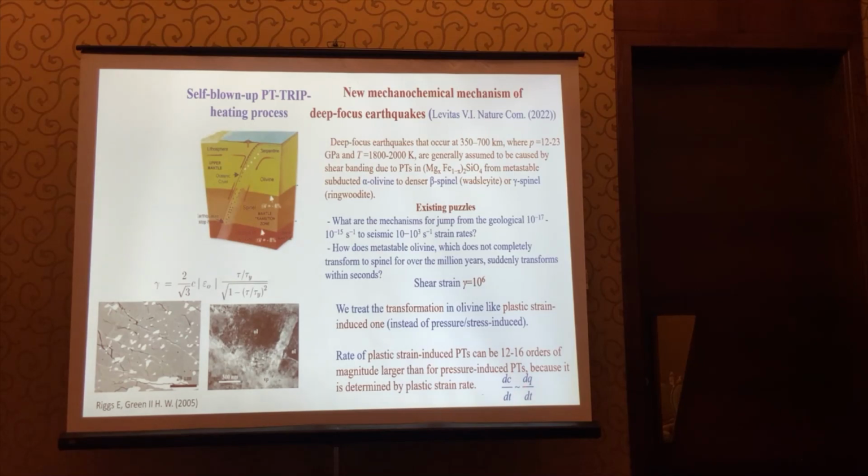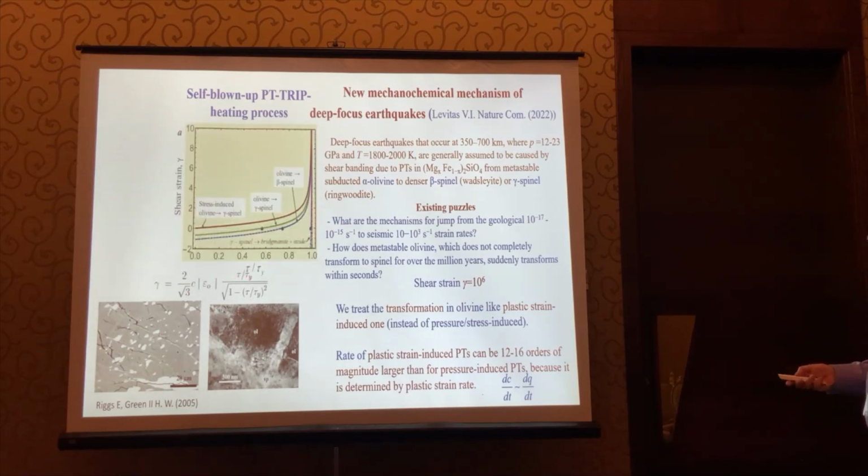So how to increase strain rate? We found analytical 3D solution for transformation-induced plasticity, or TRIP, in a shear band. And one of the results is TRIP shear, which depends on such combination of shear stress over yield strength and shear. But in shear band, shear stress is equal to yield strength. We have 0 in denominator and infinite shear strain. And this explains huge shear strain observed in nature and corresponding strain rate and even more.